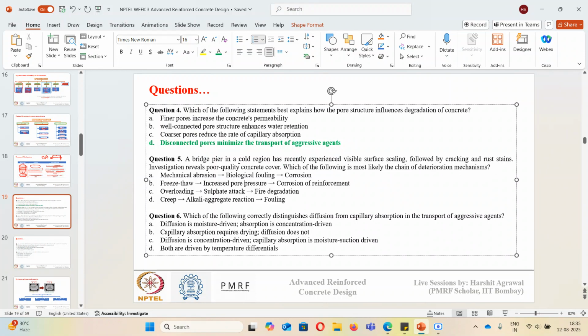Okay, so here the keywords are cold region, surface scaling, cracking and rust stains, and poor quality cover. So from this, can anyone predict what can be the reason? What is the main degradation mechanism in cold regions? It is the freeze and thaw effect. So what would have happened due to freeze and thaw effect? There would have been cracking inside concrete, which increases the pressure inside concrete.